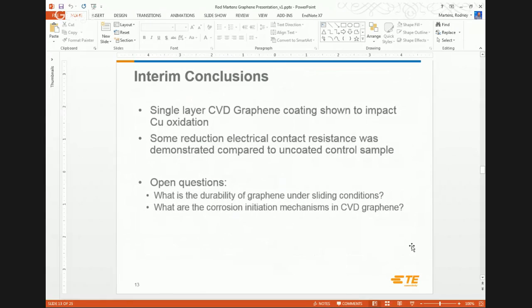Just a couple of interim conclusions then. We've kind of demonstrated that single-layer CVD graphene grown on copper can have some impact to copper oxidation and give us lower contact resistance values.